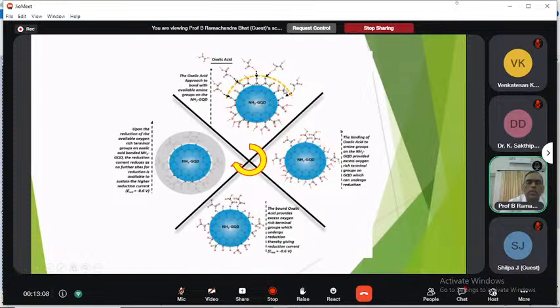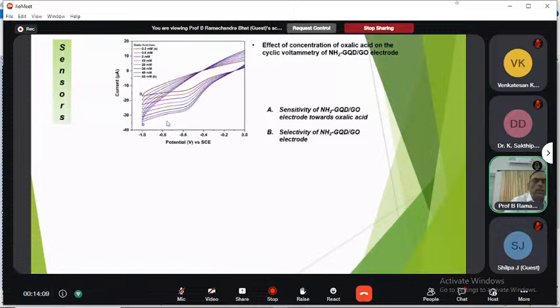Oxalic acid approaches here and forms a bond with the amino functionalized group. The binding of oxalic acid to this amino group on the NH-GQD provides an excess oxygen environment. These oxygen groups can undergo reduction, and the bound oxalic acid provides excess oxygen, which is rich on the terminal, thereby giving the reduction current. Thus, upon reduction, the oxygen-rich terminal groups on oxalic acid bound to the amino functionalized graphene reduce, as no further site is available here. So the reduction current is formed, and this can be used as a sensor for oxalic acid also.